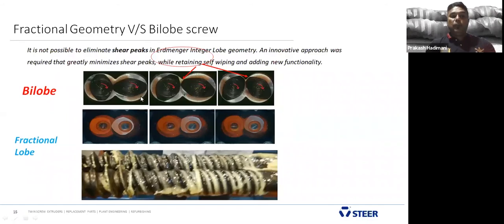If you compare bilobe technology and the fractional geometry technology, in the bilobe technology, I already explained, when the materials trap at the last section, when screws start rotating, 3% of molten material traps here. This we call a peak shear. Every rotation, the polymer starts degrading, converting to yellow color, and that leads to reduced mechanical properties.